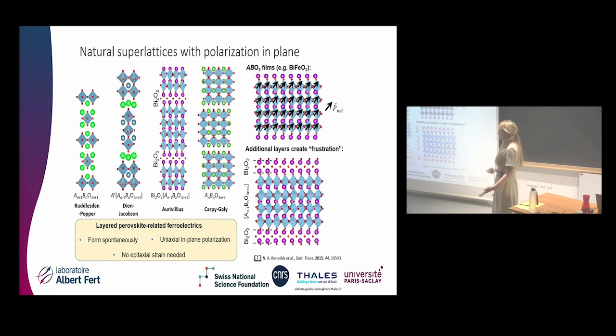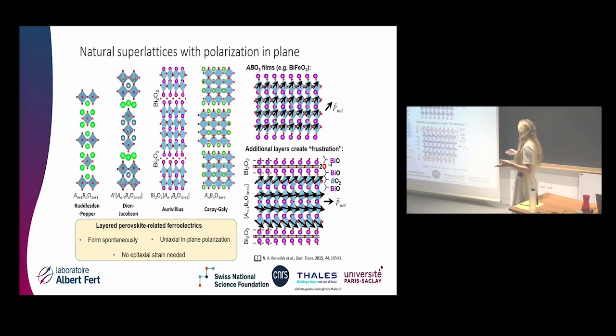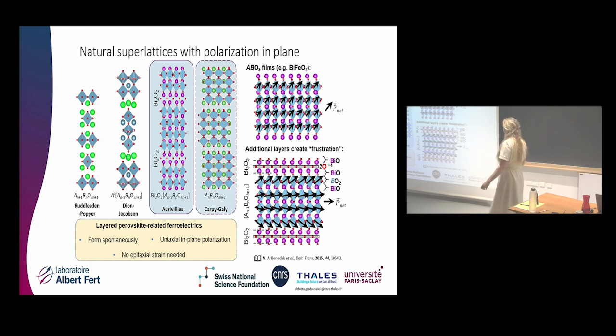If we take an example of this Aurivillius family, we will have this bismuth 2 O 2 layer, and we can break it down to something that has a double oxygen plane with a lot of negative charge. And then naturally the system will try to make use of these charges to screen the polarization. And we will end up with something like this that has in-plane polarization only. So that's how the material layering itself forces it to be polarized in the plane. And today I will mostly talk about the Aurivillius family, and hopefully at the end, if I still have time, give you some new data on the Carpy-Galy phases.